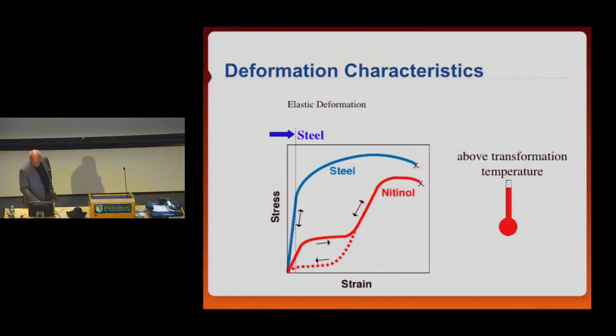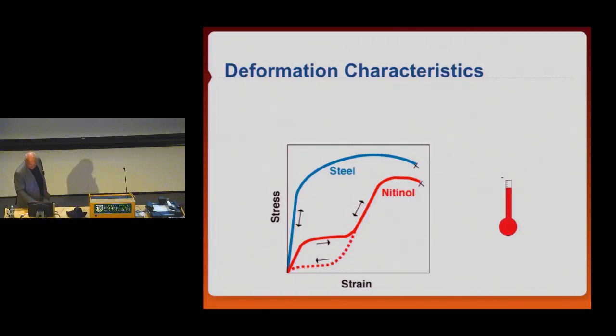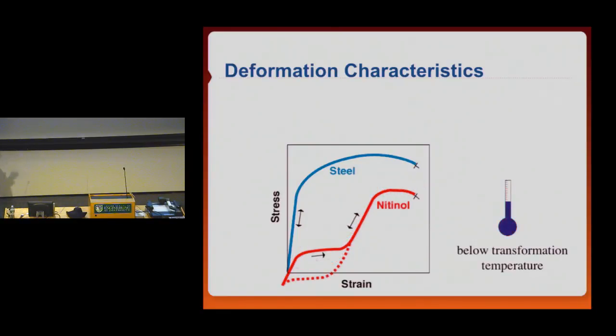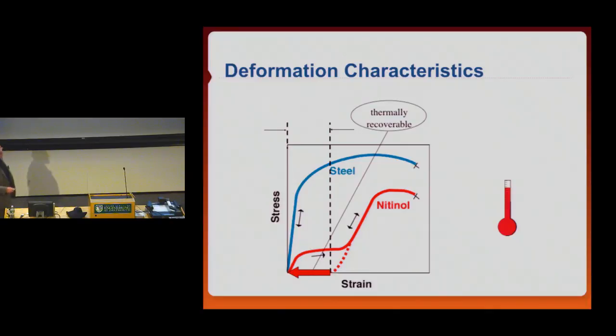If we lower the temperature, let me just do this real quick. If we lower the temperature, then we just basically move the entire curve down, and it goes below the x-axis, so that's not usable, but it's exactly the same mechanism, the exact same atomistic process. This piece that we now have that looks like it's permanently deformed, this can be thermally recovered. So if you heat the sample up back to where we were, then you would move this curve up, and the deformation is recovered.